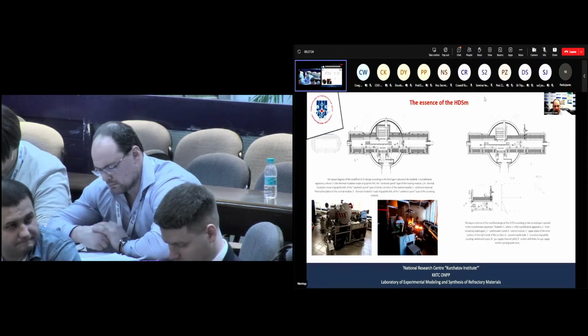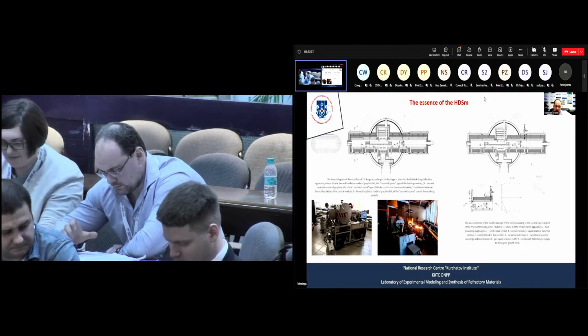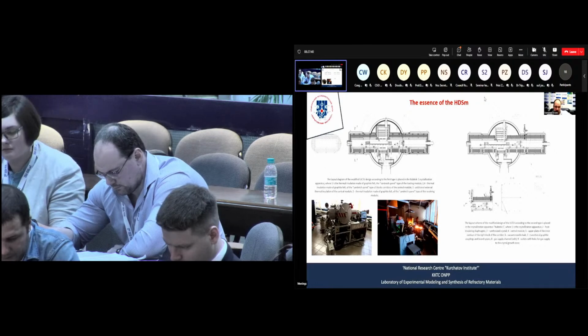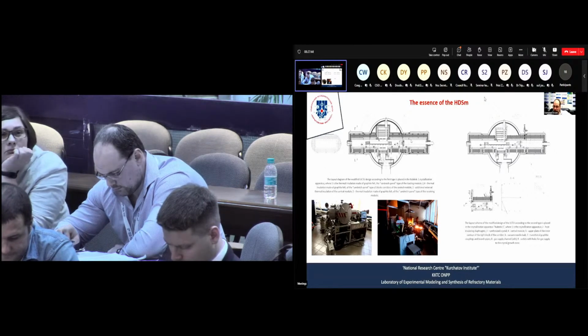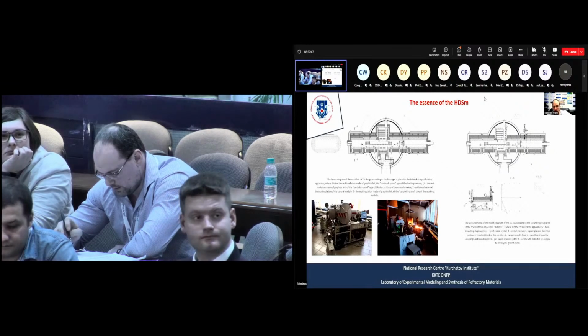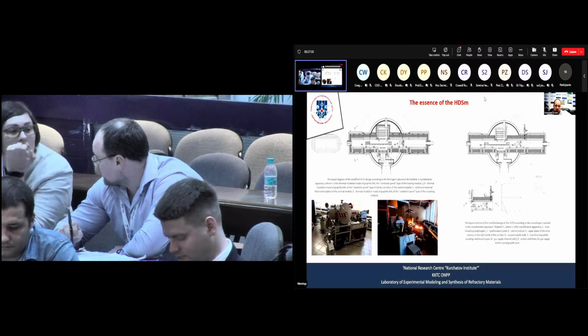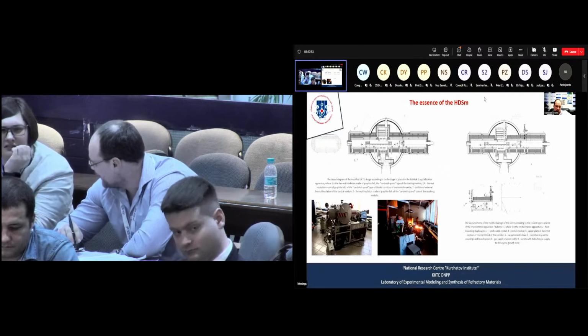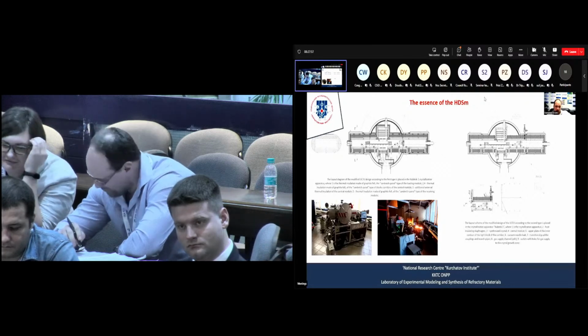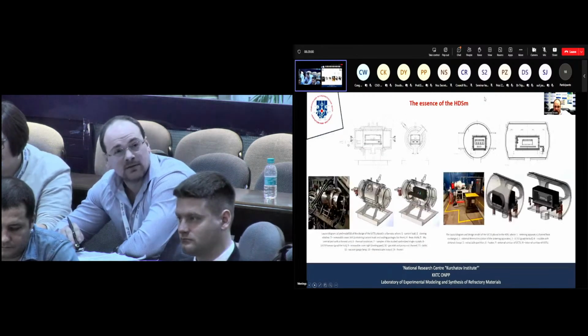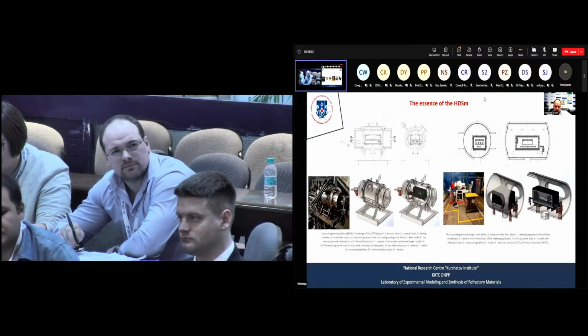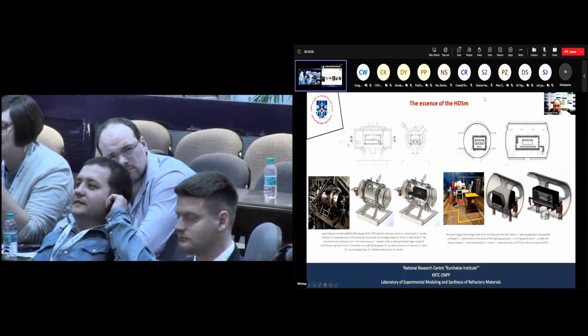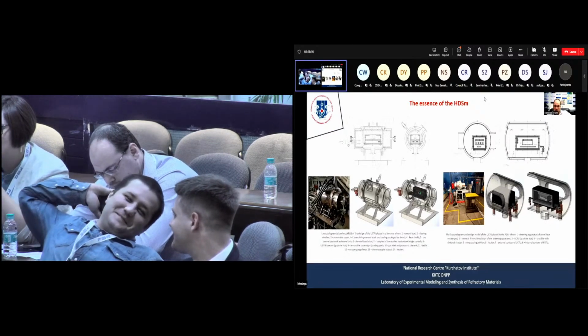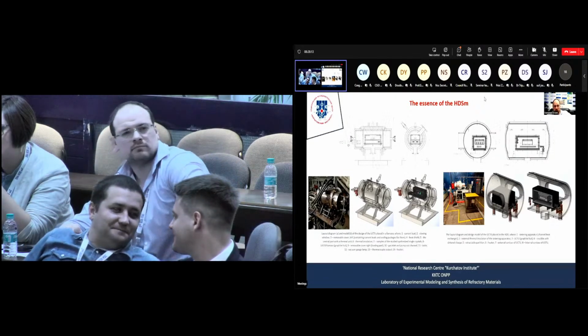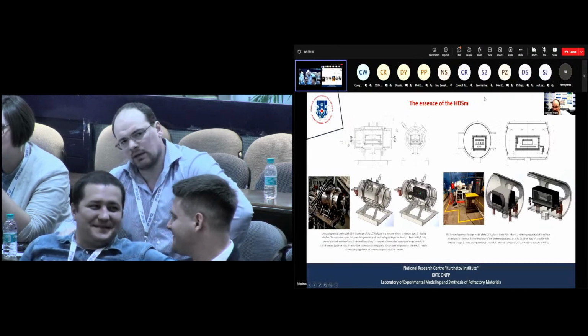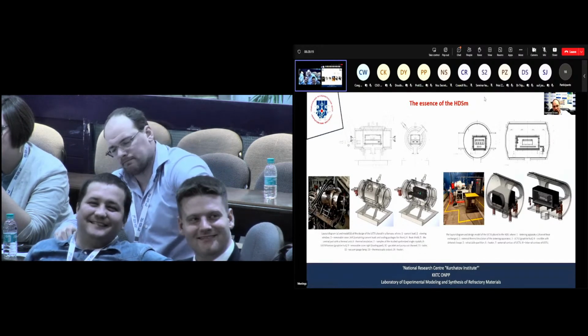Blocks are easily assembled with each other according to the Lego principle. This combination forms an integral design of the thermal unit in the form of a common heat insulating volume. This volume makes it possible to reduce the total cost of the crystallization process by growing crystals without additional energy. Additional equipment was also developed: an auxiliary dry briquetting apparatus (DBA) is depicted there with a thermal unit for obtaining solid anhydrous cake, and a high temperature vacuum furnace. A thermal unit for studying color centers was also developed.